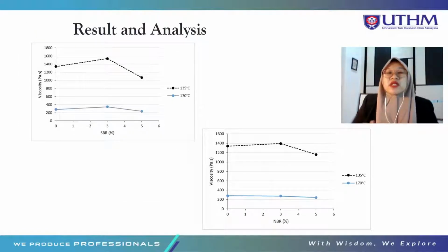This is the result and analysis for viscosity values of coagulum modified asphalt binder. The viscosity values were recorded at temperatures of 135 degrees Celsius and 170 degrees Celsius. The viscosity values for both SBR and NBR coagulum modified asphalt binder decreased as the temperature increased from 135 degrees Celsius to 170 degrees Celsius.